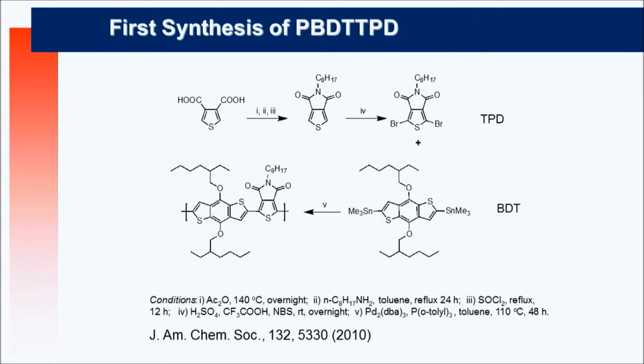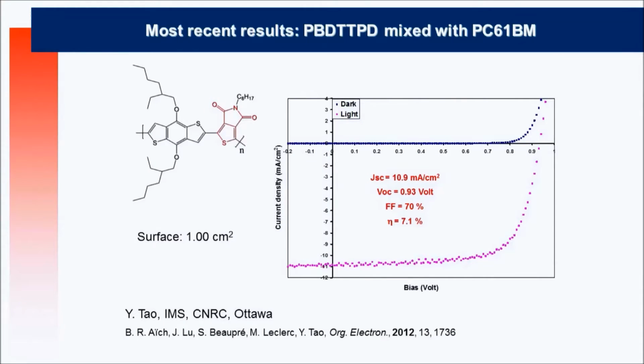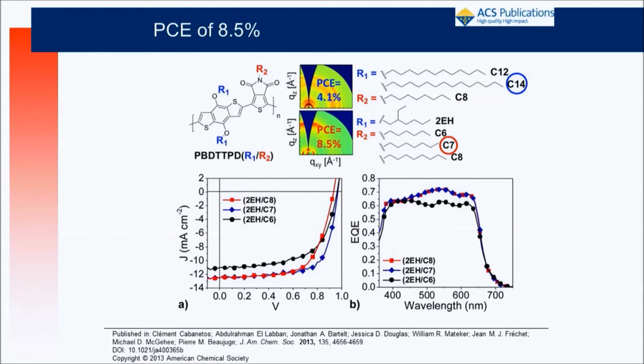To make a high molecular weight polymer, you have to rely on the so-called Stille coupling. So you need tin derivatives to make high molecular weight materials. It's not perfect, but we were able to get this polymer. And with Y. Tao at IMS and CNRC, we were able to reach up to 7% with this polymer. And Beaujuge, McGehee, and Fréchet at KAUST. If you really want a strong competitor in the field, KAUST is a good place. King Abdullah University of Science and Technology. They reported that if you slightly change the side chain here, you can get up to 8.5%.